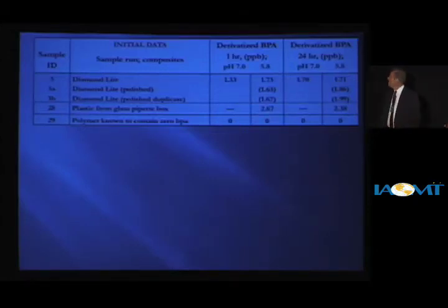For the initial results I had run at first, there was some concern about removing that oxidative layer by polishing. So I took some Diamond Lite and ran it, polished and unpolished. And as you can see, the precision was awesome. But it also told us that we didn't need to polish all the samples because it wasn't going to make any difference. So the rest of the samples were run unpolished.